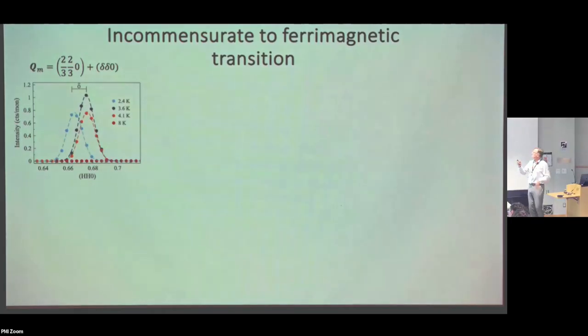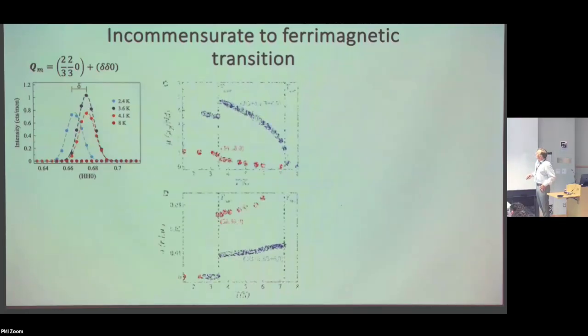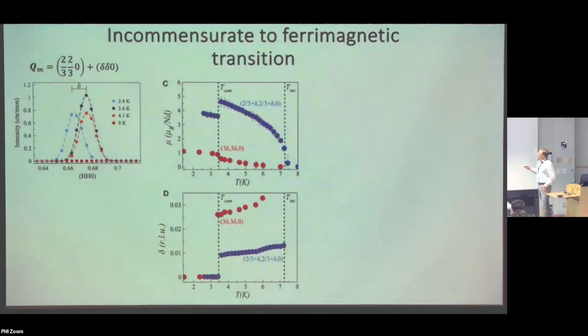So now it's being forced into this commensurate position in order to get a fully polarized rare earth site. And I think one thing I just want to show here is that the wave vector slides with temperature, and that's also a fairly normal thing. As the exchange field grows, there's a modification of the electronic band structure that changes the interaction, and then you have this kind of thing taking place.